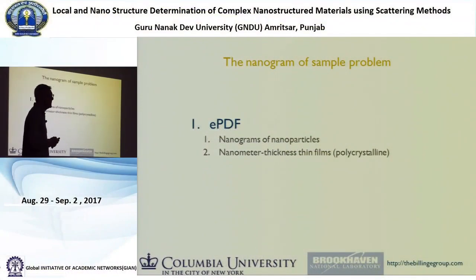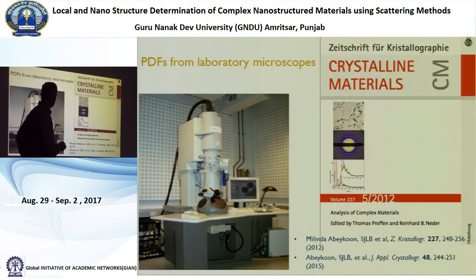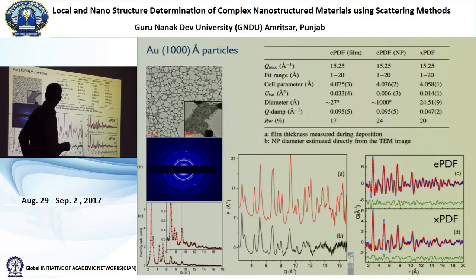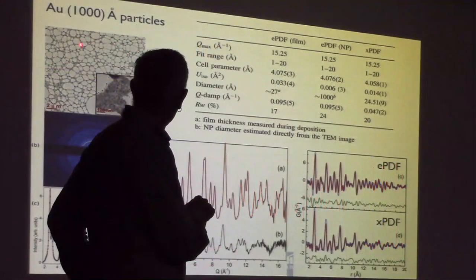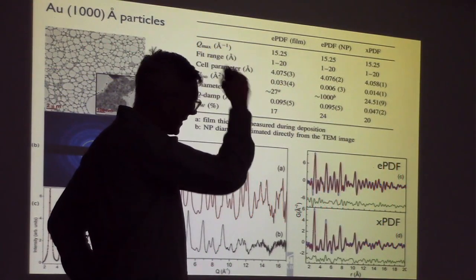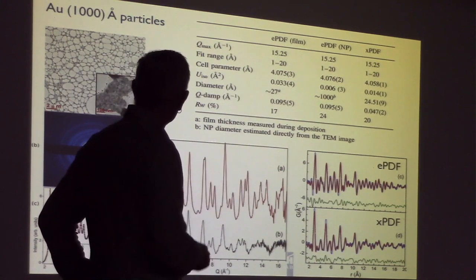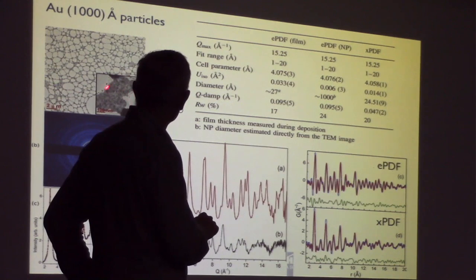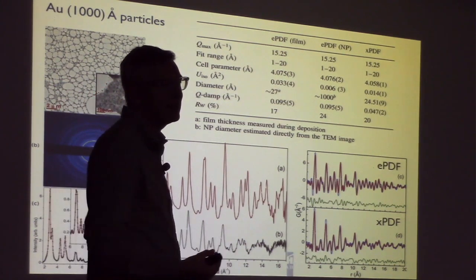Now let's say you only have nanograms of material. What do you do? So what we were able to do in that case was actually we put it in an electron microscope. So it's basically a laboratory microscope, and you take the material. Let's look at the next slide. Yeah, it's easy to see here. So this is a standard microscope sample support. It's called a holey carbon film. So it's kind of a thin web-like film of glassy carbon. And we drip some gold nanoparticles in solution on there, and we let the solvent evaporate. And so these tiny dots on here are actually gold nanoparticles, and we can image them in the TEM.